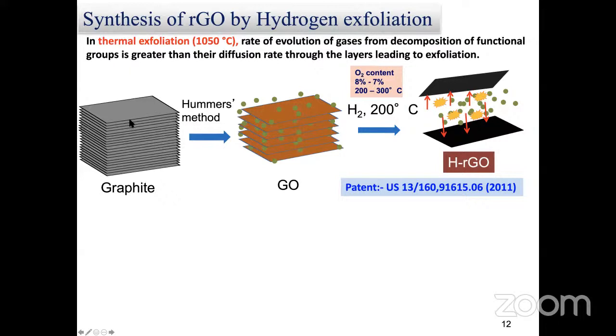But the problem here is that the van der Waals interaction is very strong. So it is not possible for you to do that, except that you can use a Scotch tape technique to peel off the single layer, but it is very tedious and you cannot get it on a large scale. So we want to make it on a large scale. So what we have done is that we have used Hummers' method, where we allow the graphite to interact with the oxidizing agent and acid, so that the separation between successive layers is increased from 0.34 nanometer to 0.8 nanometer. That means I'm weakening the van der Waals interaction, but the functional groups have been added.